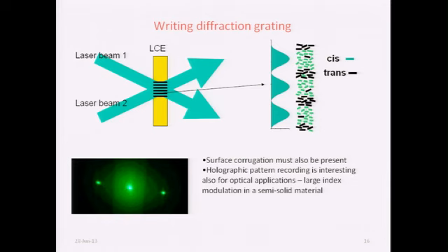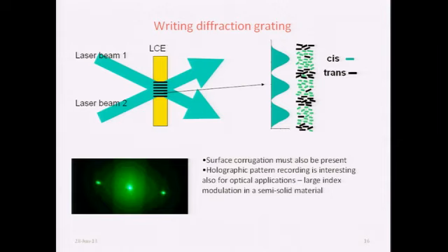And this, of course, produces, through the dependence of the index of refraction on the nematic order parameter, relatively large, up to 0.2 or something like that, modulation of both indices of refraction, ordinary and extraordinary. The extraordinary produces somewhat larger modulation. Now, I have to remark here that, of course, all these phenomena are also strongly polarization dependent.